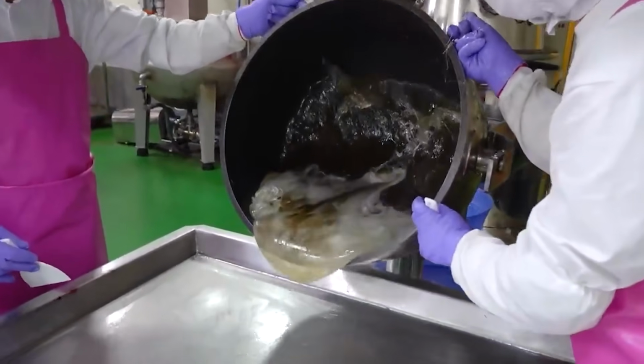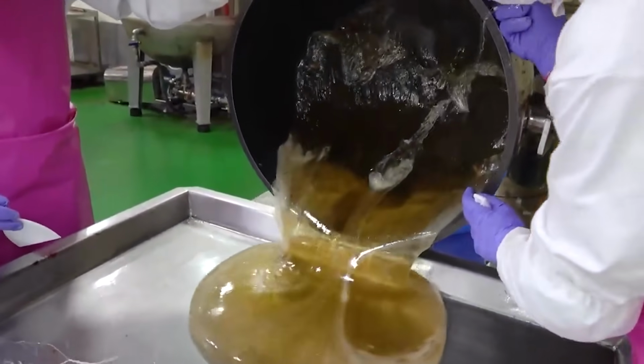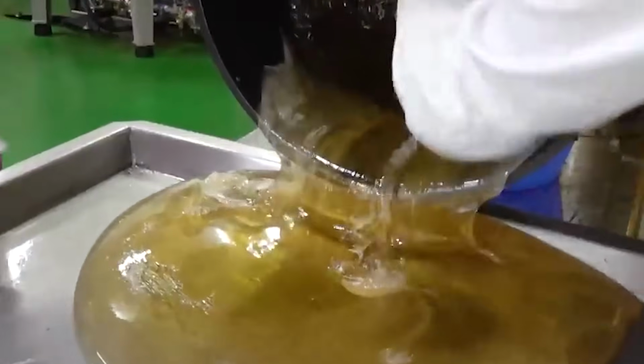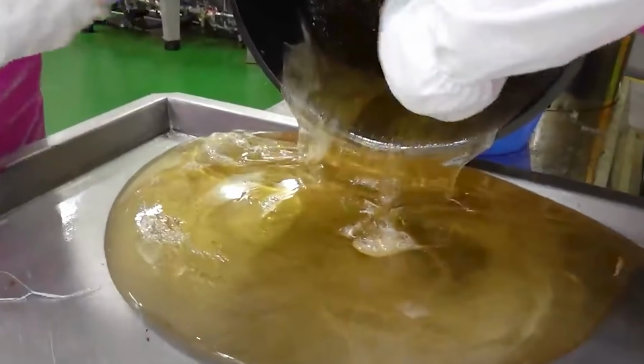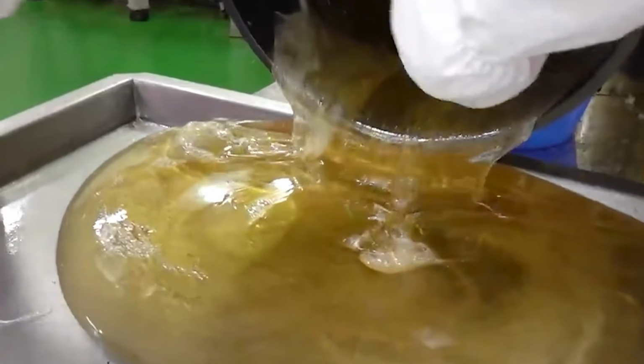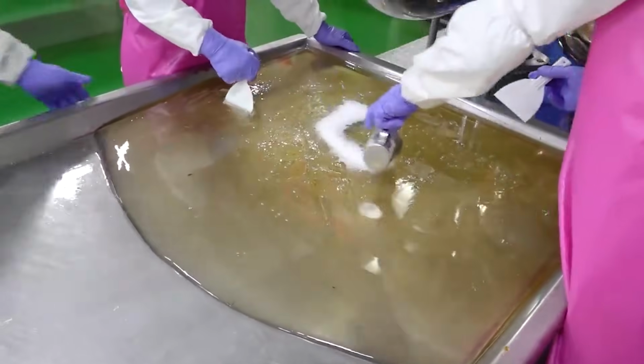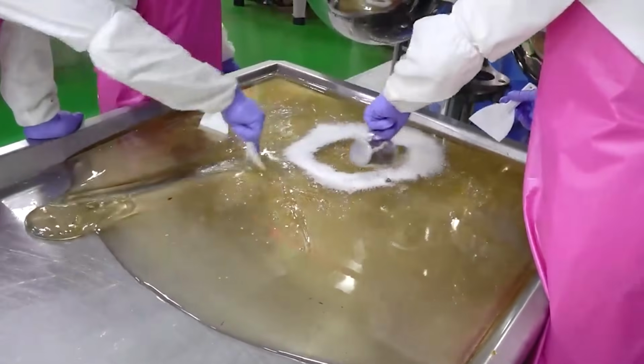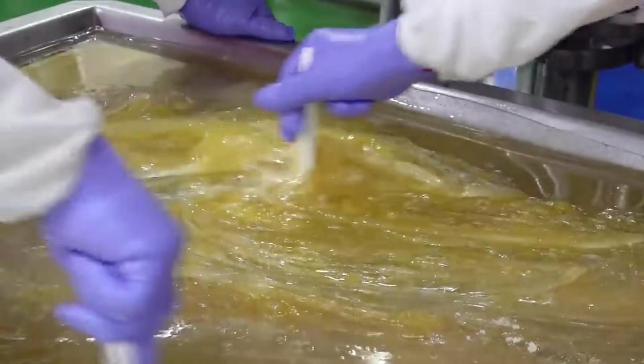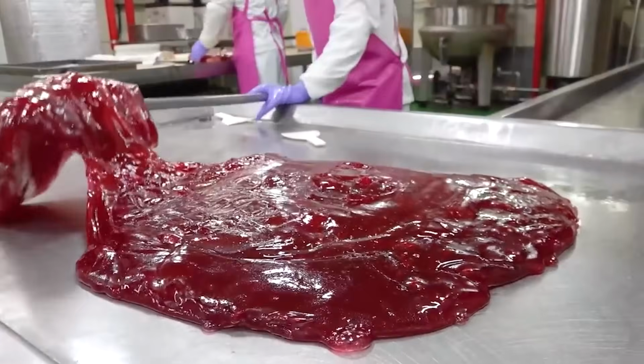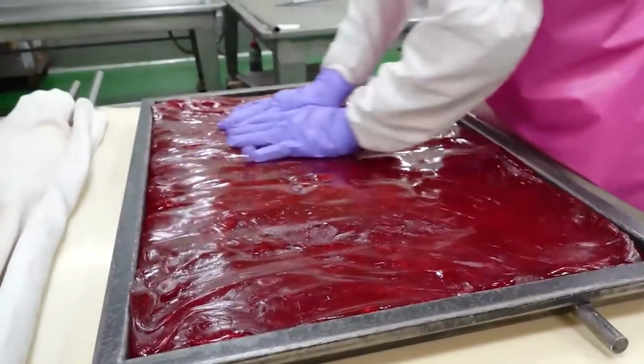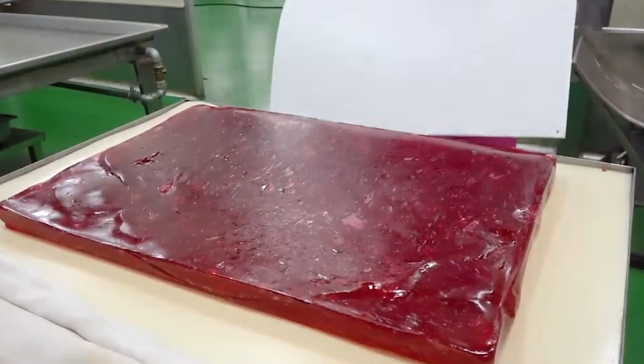Casting converts liquid candy into a solid glass that can be fractured. The hot syrup is deposited onto a moving steel belt or onto casting trays as a thin sheet. Deposit rate and belt speed set sheet thickness. Thickness is important because it affects cooling rate and fracture size. A thicker sheet cools slower and can form internal stress gradients. A thinner sheet cools quickly and can become too brittle at the surface.